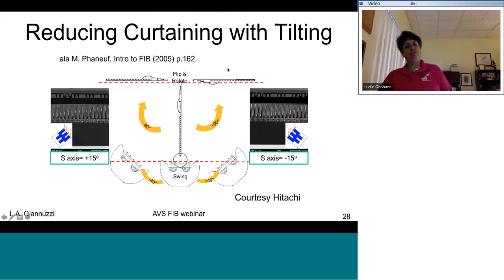Okay, so the way you can reduce curtaining is with tilting, and this was first introduced by Mike Phaneuf. Again, this is shown in the FIB book. So you can do this inside of your FIB. In some cases, unless you've got a special rocking stage, when you rotate and tilt, you won't be able to see what you're doing with the FEM. And so some people have incorporated these special rocking stages. I believe Hitachi, I believe Tescan have these special substages, these rocking stages, that when you tilt and FIB mill from different directions to remove the curtaining, you can still see what you're doing with the FEM.